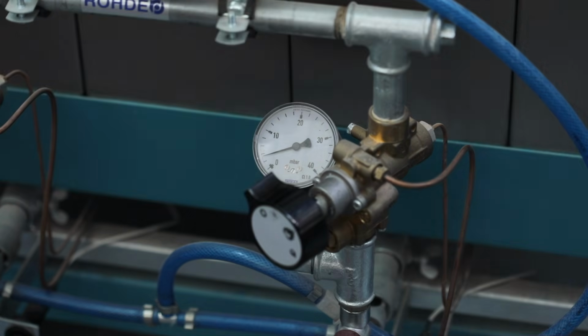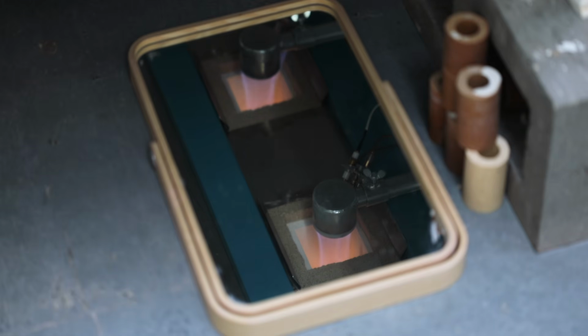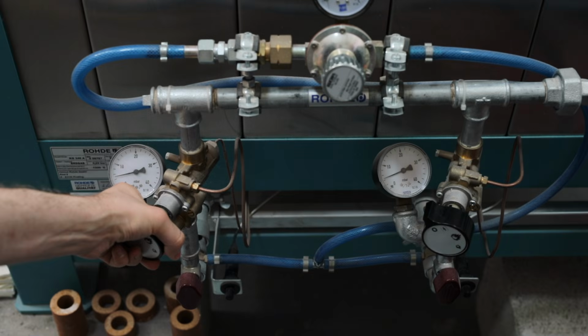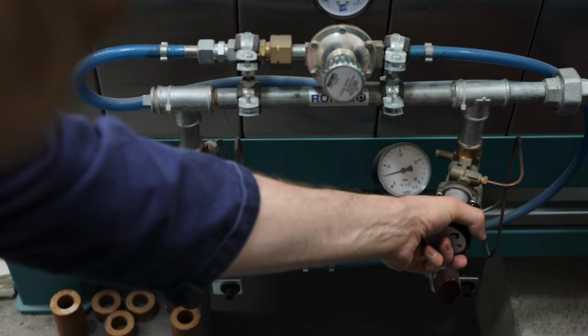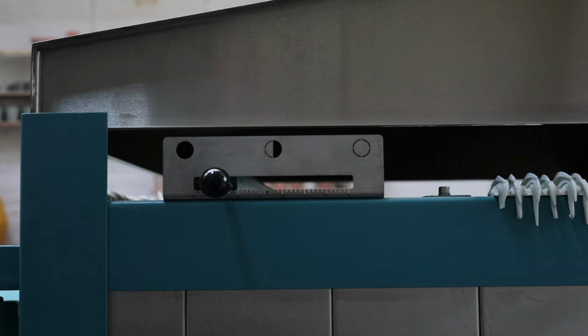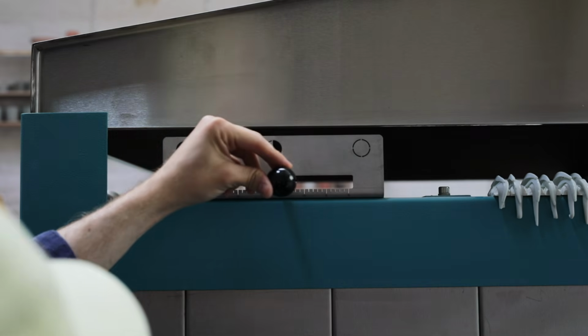But it isn't always down to the firing itself, and how you load the pots inside might make quite a big difference. During the very early stages of the firing, I have one burner that has the tendency to switch off, and so, for about an hour or so I place a mirror on the floor, just so I can easily glance down to see what the flame is doing. And then, at exactly 860 degrees Celsius, I initiate reduction.